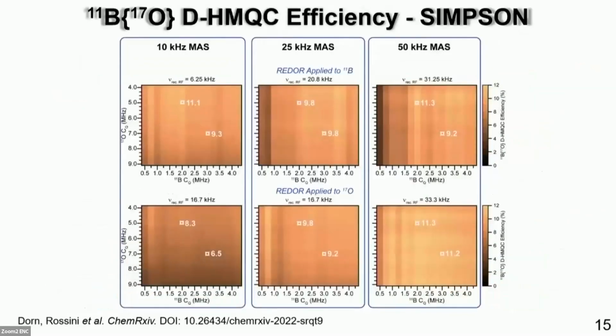We lastly numerically investigated the effects that the quadrupolar coupling constant for both boron and oxygen and the magic angle spinning frequency have on these D-HMQC efficiencies. Well, you can see that it is generally robust to both the quadrupolar coupling constants and the MAS frequency, which again further demonstrates the general applicability of these type of experiments for many different spin systems. So now that we have these boron-oxygen experiments on hand, we actually want to utilize them to further determine structure within materials of interest.